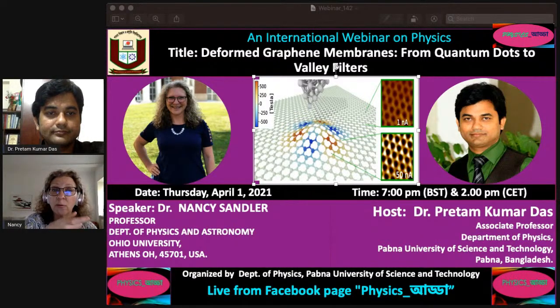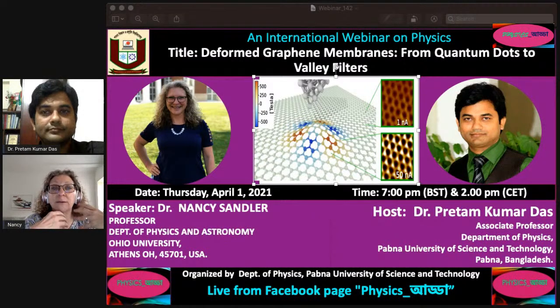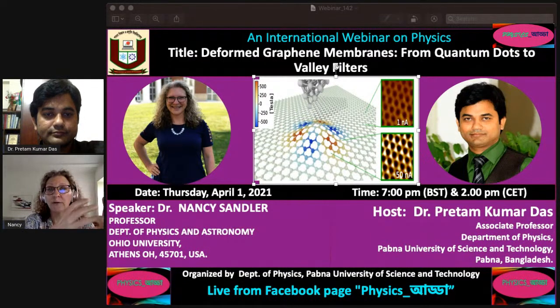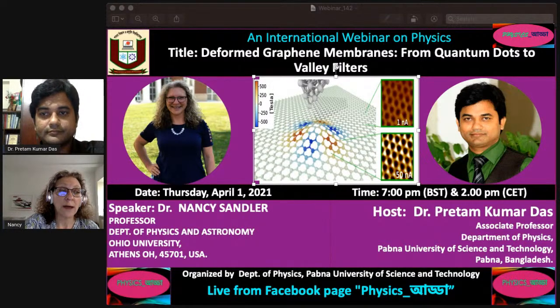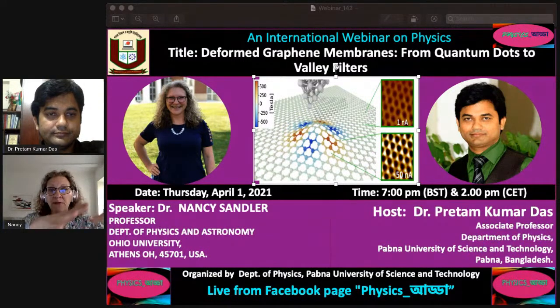The problem with this way of making a flake, which is a finite sample of graphene, is that it's completely uncontrolled: the size of the flake that you end up having, the type of termination, and also the purity, because you may create defects in the middle of the flake. So people have developed other methods to grow graphene. The one that could have potential applications is a technique called CVD, chemical vapor deposition, that creates in reality more polycrystalline samples. That is, different graphene flakes that are attached to each other but have different crystalline orientations.